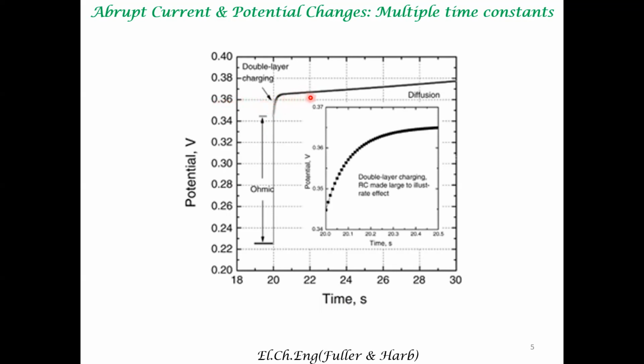Okay, so the capacitative current decays, and the potential change to maintain the constant current is just because of diffusional processes. So in a typical process, when you want to operate at constant current, there are three processes: ohmic activation processes, capacitative processes, and diffusive processes. And all three have different time constants. Because of this, there is coupling of time constants, and what you measure is a convoluted result. It can be deconvoluted to identify the characteristic physicochemical processes that occur at the electrode-electrolyte interface.